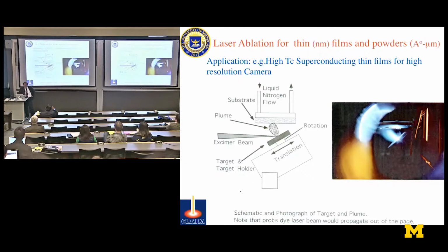As a first example, you can even make nanocrystalline material using this. One of the techniques we developed was essentially using the laser to ablate the material, collect it in liquid nitrogen-cooled plate, and most of the material, even the example I'll be giving, niobium aluminide, I can make nanocrystalline and maintain the composition. Now, why am I saying that? Niobium melting point is higher than the boiling point of aluminum. So if I can maintain the stoichiometry and make a nanocrystalline material, that gives me a tool.